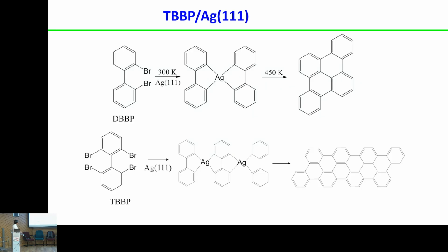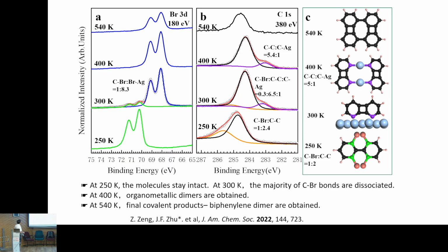Then we think these molecules didn't rotate to go in this direction, and we put bromine atoms on both sides. The initial idea was to see whether we can form graphene nanoribbons, but it's actually different. With synchrotron radiation photoemission, you can see at low temperature the molecules stay intact, but when you warm up to 300 Kelvin, this debromination reaction happens.